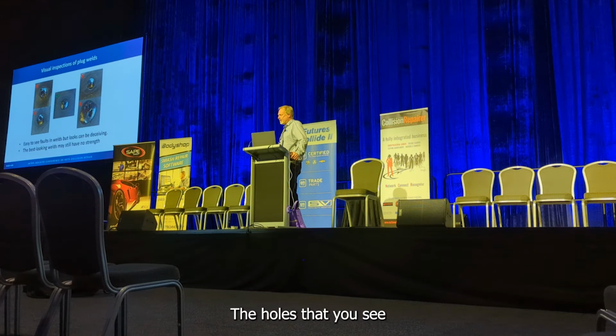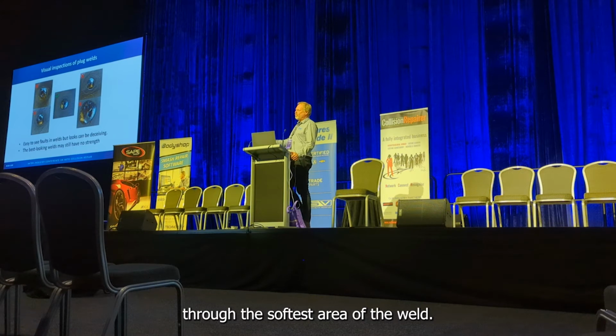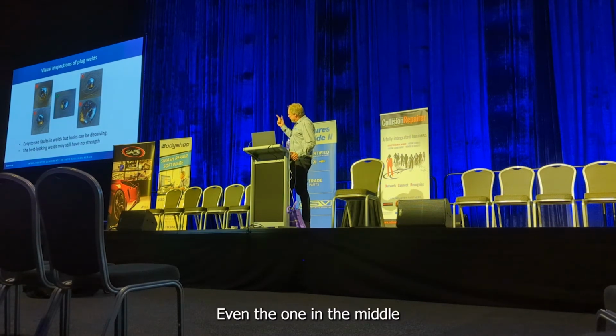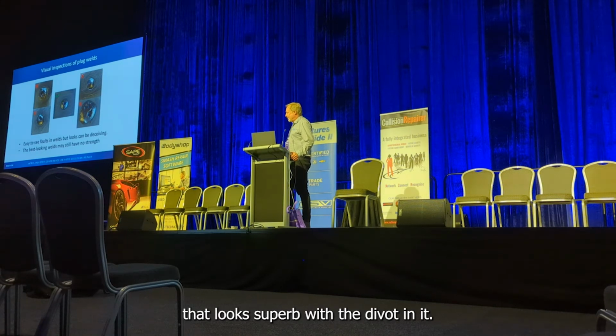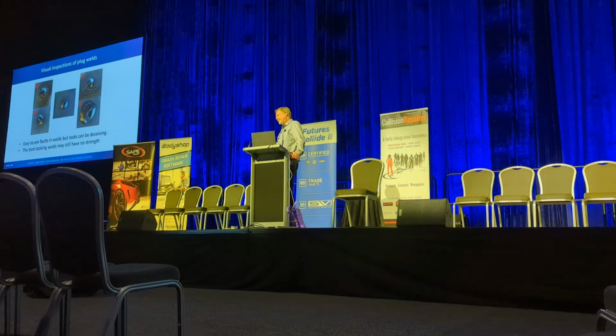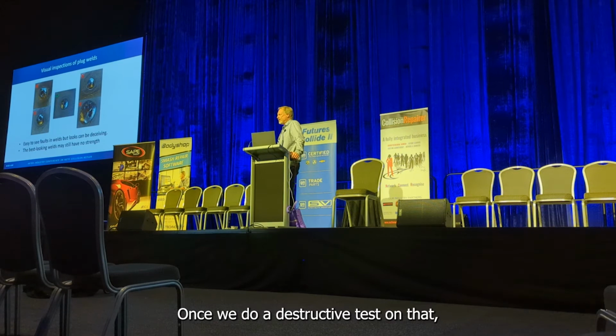The holes that you see in these plug welds visually, that is because there's no penetration into the base plate, into the panel it's being welded to. So the hot air trapped under the molten puddle is coming back out through the softest area of the weld. Even the one in the middle that looks superb with the divot in it, once we do a destructive test on that, we can find issues within the weld core itself.